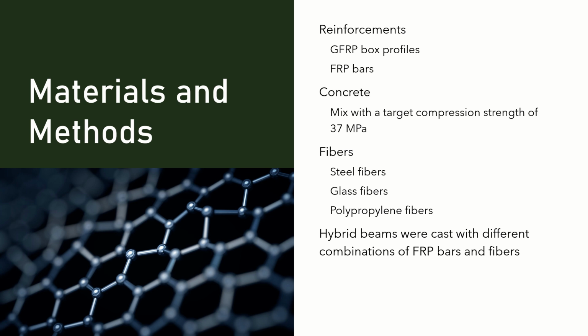In our study, we used several types of reinforcements. These included GFRP box profiles and FRP bars made from carbon, aramid, glass, basalt, and steel. The concrete mix had a target compressive strength of 37 megapascal. We also incorporated different fibers into the concrete, which were steel fibers, glass fibers, and polypropylene fibers. We cast hybrid beams with various combinations of these FRP bars and fibers to evaluate their performance.